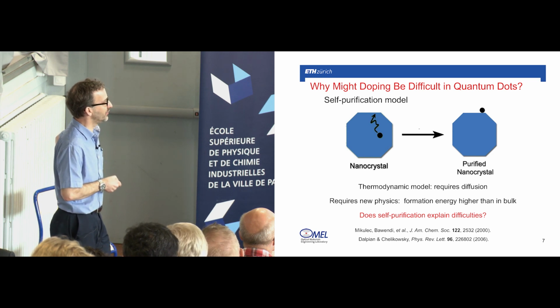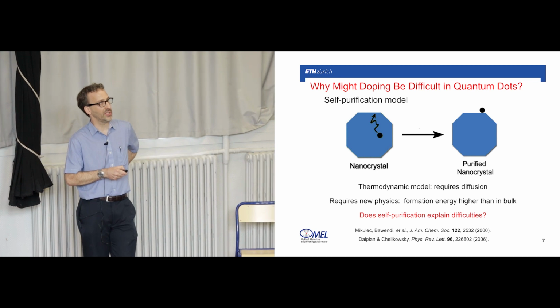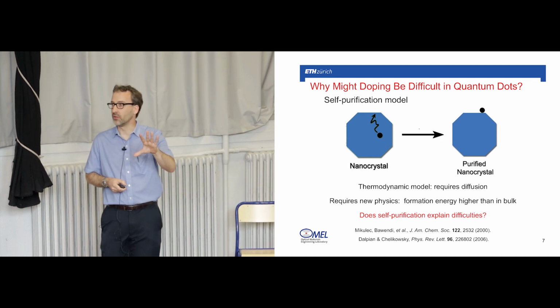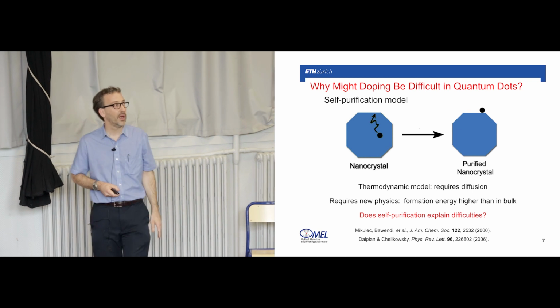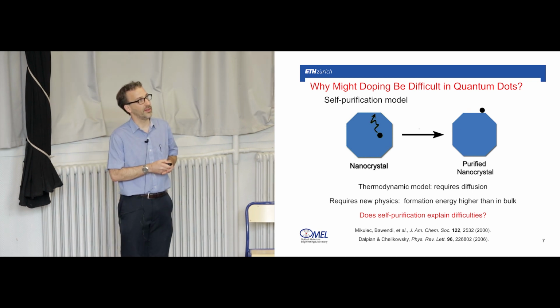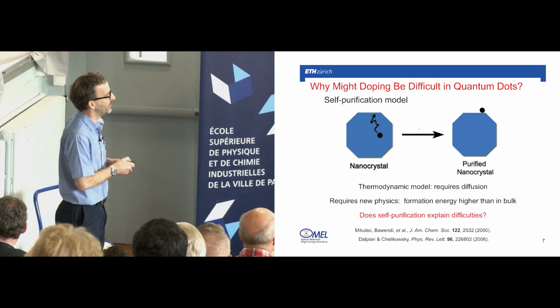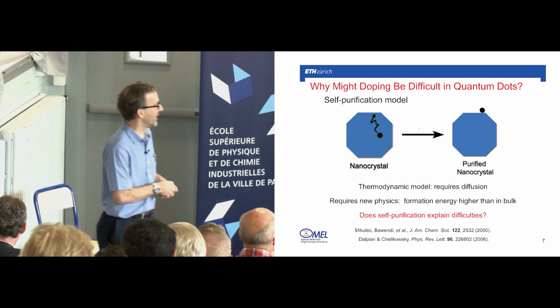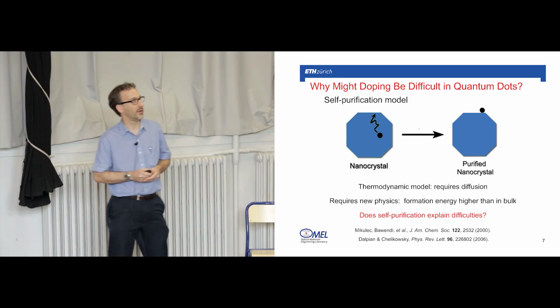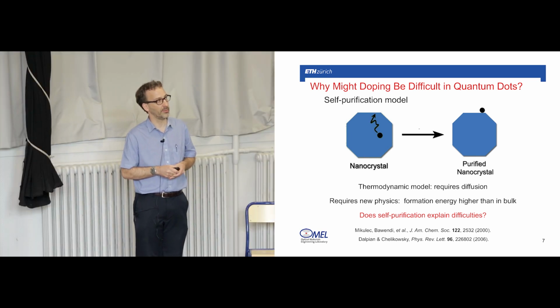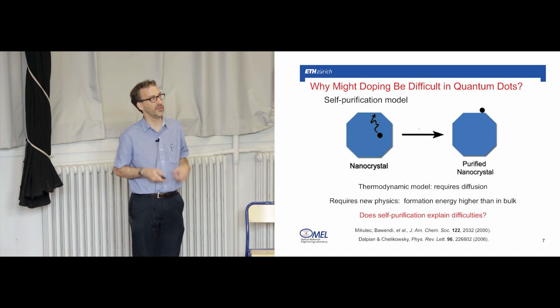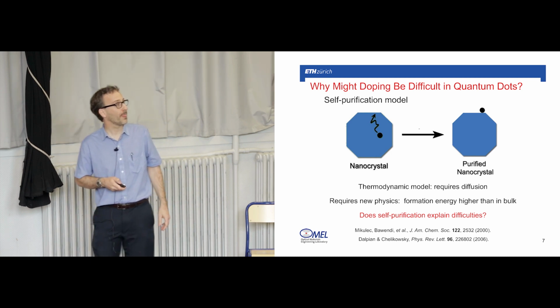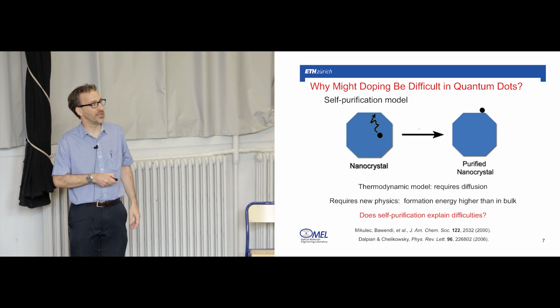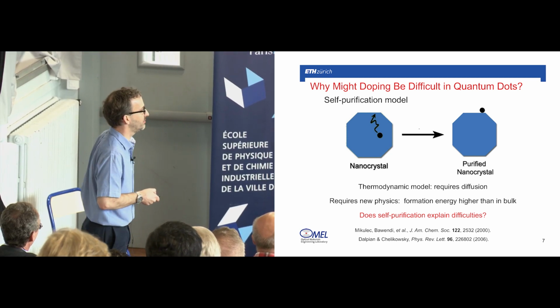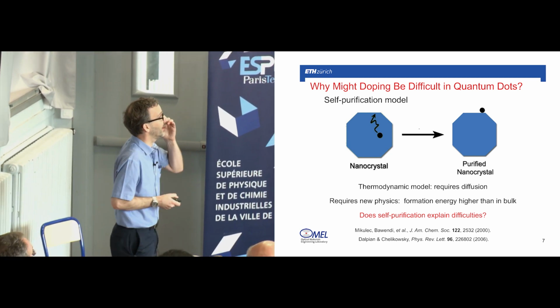And it also requires new physics, because if the formation energy of this impurity in the bulk material is sufficiently low that you can dope the bulk, then this implies that the formation energy is going up in the nanocrystal, and that's what's driving it out. There had been some theoretical reports that the formation energy did go up with decreasing size. Okay, so the question now is, does this self-purification model explain the early difficulties people were having?